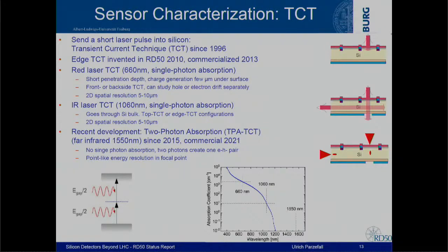If you switch to an infrared laser, you get much less absorption, so you can go all the way through the silicon, or in this edge TCT configuration, shine in from the side.